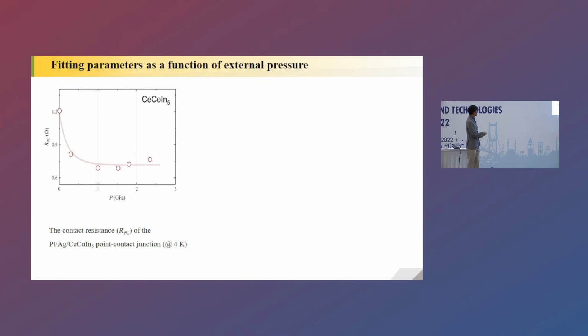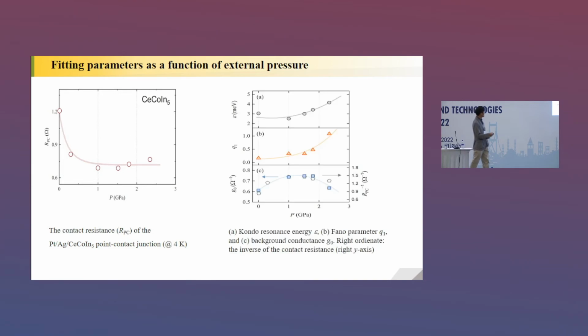Okay, so some of the fitting parameters that we use. This is contact resistance as a function of pressure. Initially it drops, and then pretty much is consistent. And then the Kondo resonance energy and the Fano parameter are almost flat, gradually increasing with increasing pressure, as expected, because when you apply pressure, you increase hybridization. And then the background conductance and inverse of the contact resistance are pretty much consistent.